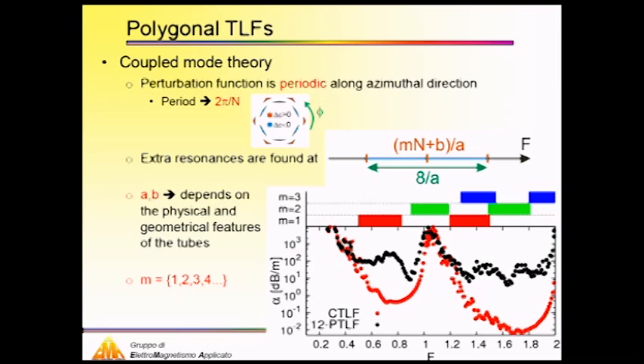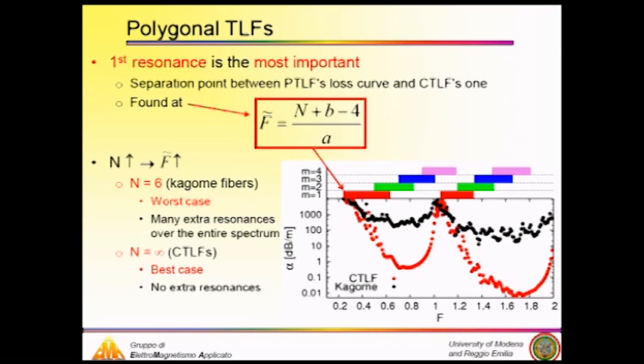So here we can apply this model to a comparison between the circular case and a 12-sided polygonal tube lattice fiber. Rectangles here represent the application of this formula with different M values. And as you can see, they're perfectly able to predict the position of this extra resonance. So what matters most, actually, is the position of the first resonance, since it's the first one that appears in the frequency.